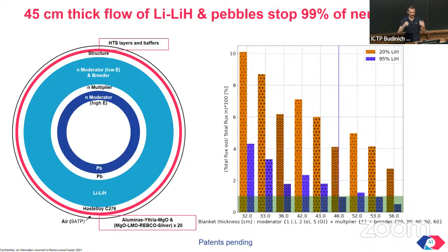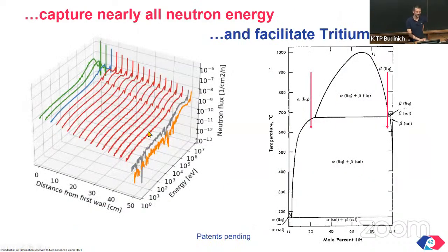And so what happens is when we apply our current to the liquid metal, these electrically insulated pebbles are not subject to the J cross B force pushing outward. So instead, they tend to accumulate inward, where they are most needed, both for the attenuation at high energy and for the multiplication. This choice of materials in a relatively modest thickness of 46 centimeters allows us to attenuate, to absorb 99% of the neutrons. So only 1% of the neutrons passes through, and a much smaller fraction of the neutron energy passes through. This is the energy spectrum of neutrons as a function of distance traveled across this medium.